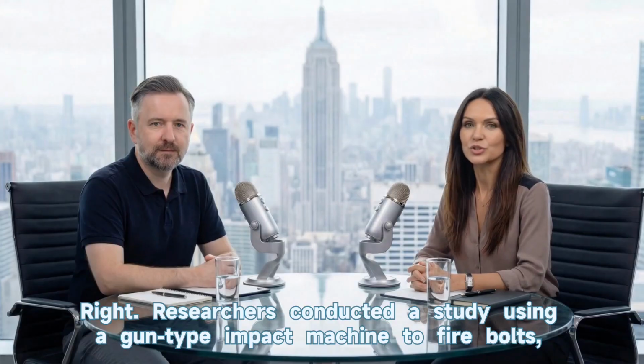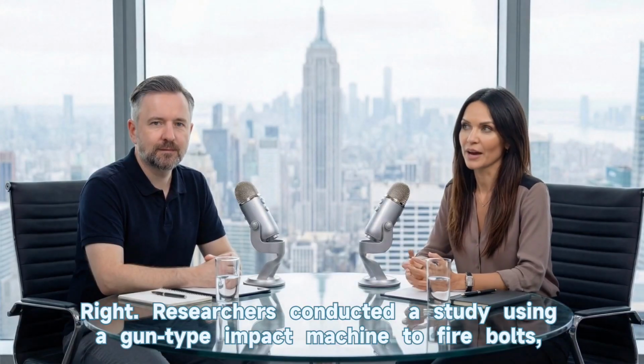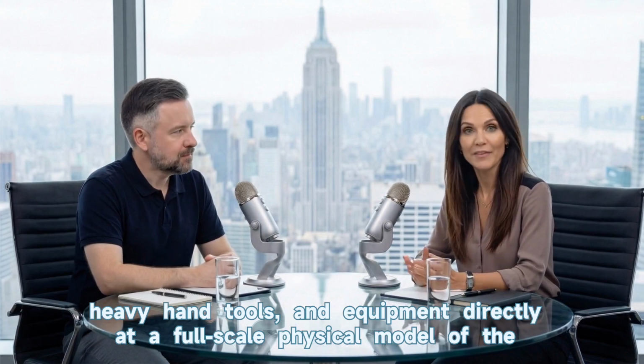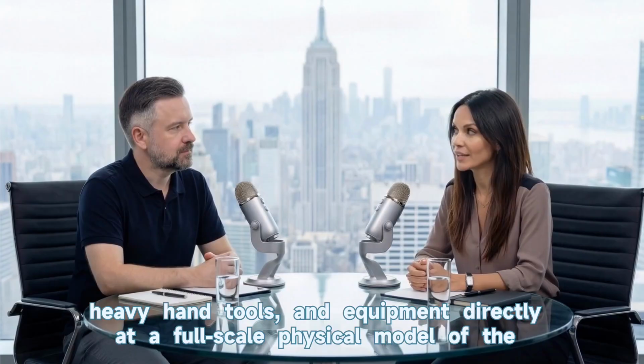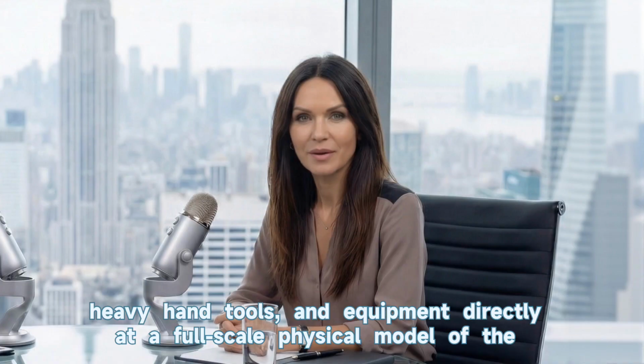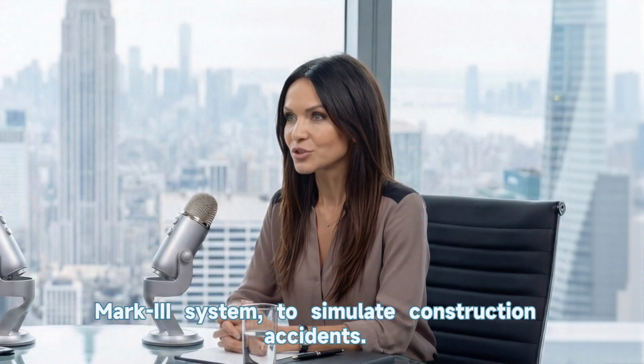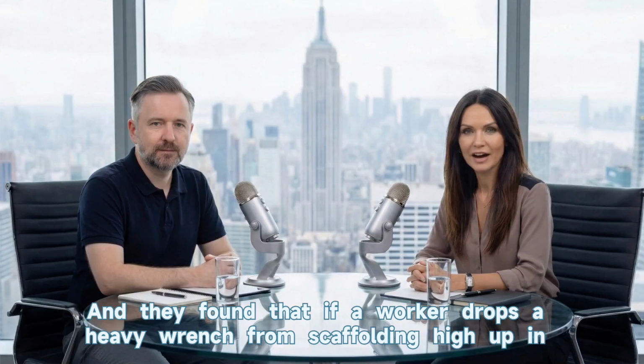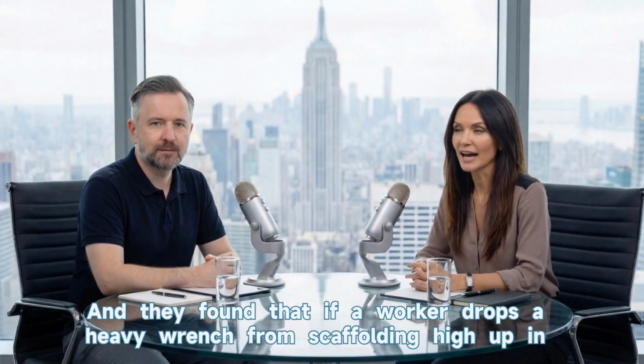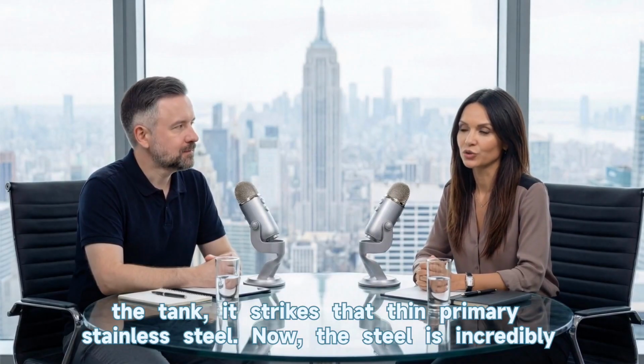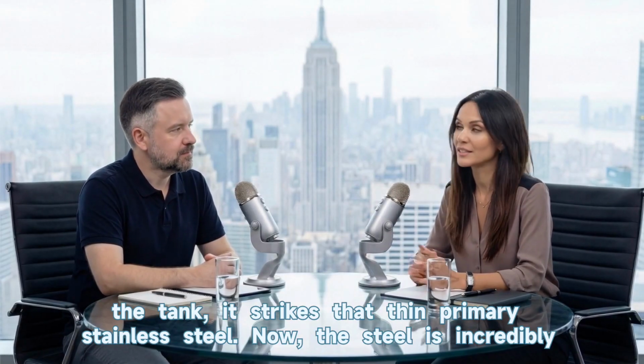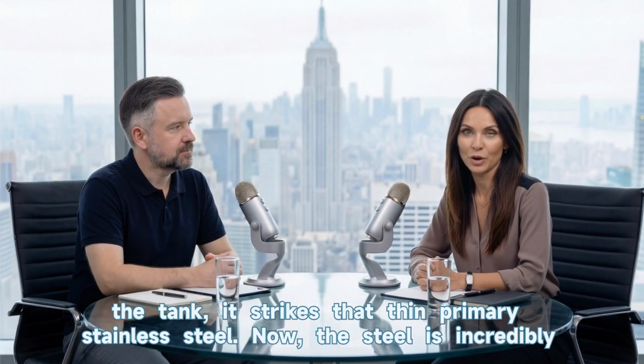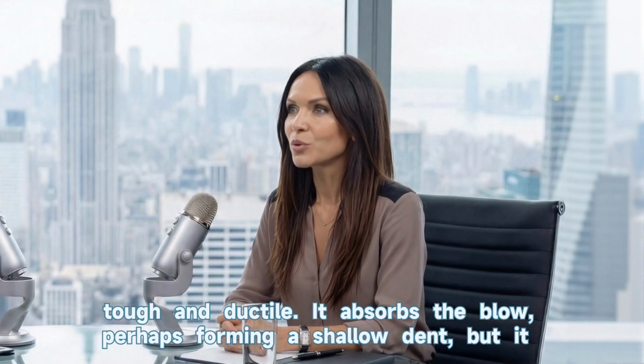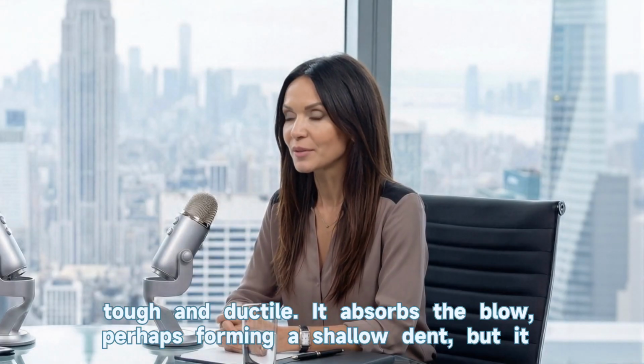Right. Researchers conducted a study using a gun-type impact machine to fire bolts, heavy hand tools, and equipment directly at a full-scale physical model of the Mark III system to simulate construction accidents. And they found that if a worker drops a heavy wrench from scaffolding high up in the tank, it strikes that thin primary stainless steel. Now, the steel is incredibly tough and ductile. It absorbs the blow, perhaps forming a shallow dent, but it does not puncture.